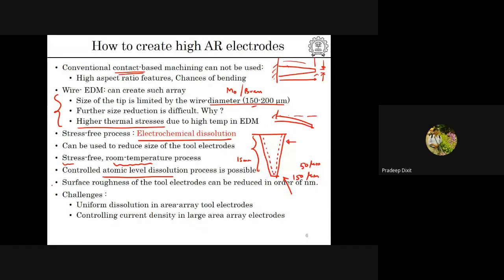The second thing is that besides the size reduction, you can also improve the surface smoothing. As you know, in the EDM process, because this is a high temperature process, there is a lot of surface roughness. If you want to reduce it, you can use electrochemical dissolution or an electrochemical finishing process. Now the challenge is that all these things which I just mentioned are fundamentally possible, in theory you can do that, but when you go to a real application, you have a lot of challenges. The very first challenge is: can we get a uniform dissolution? What do you mean by uniform dissolution? If you look at this picture which I'm drawing now, this is my initial profile, and this is the final profile here. What I want is to remove 50 micrometer of dissolution from all the points.